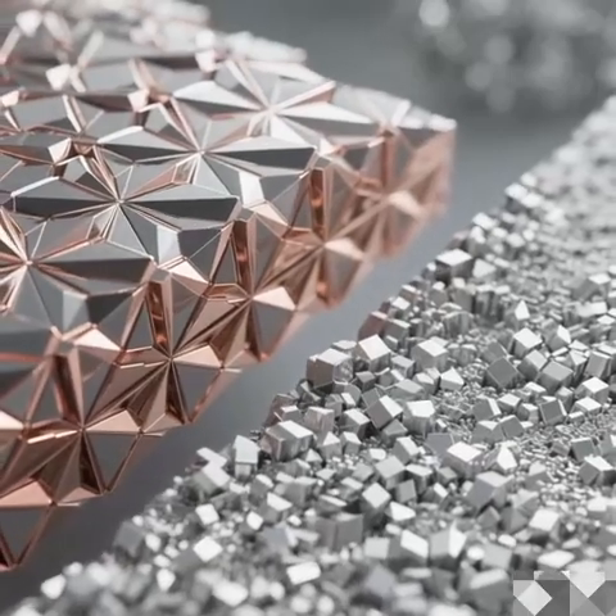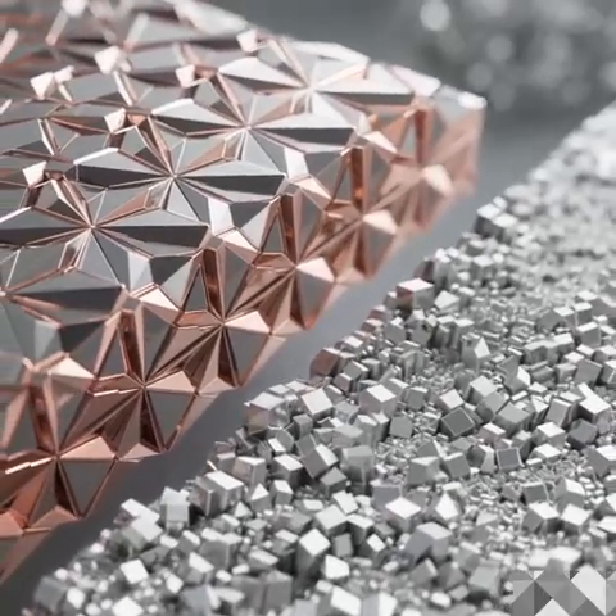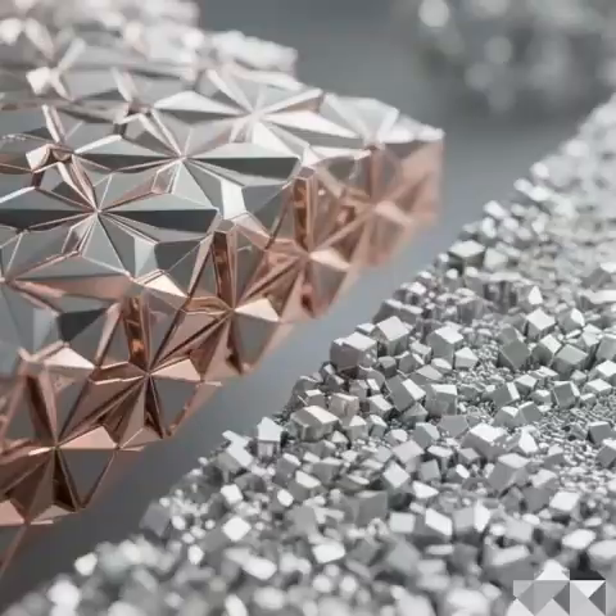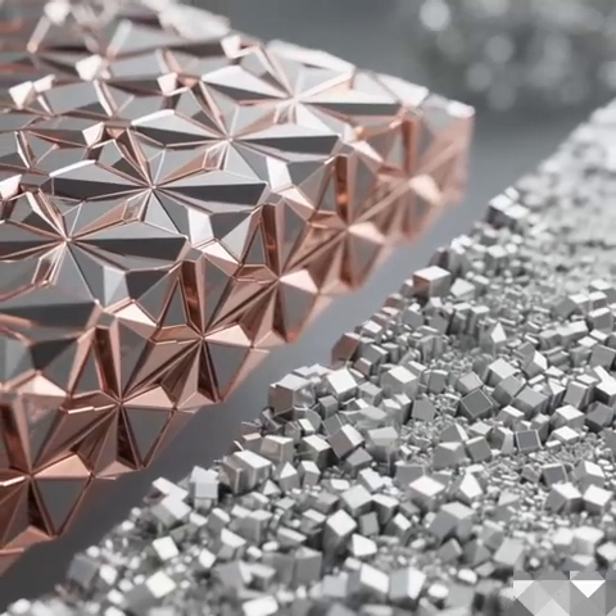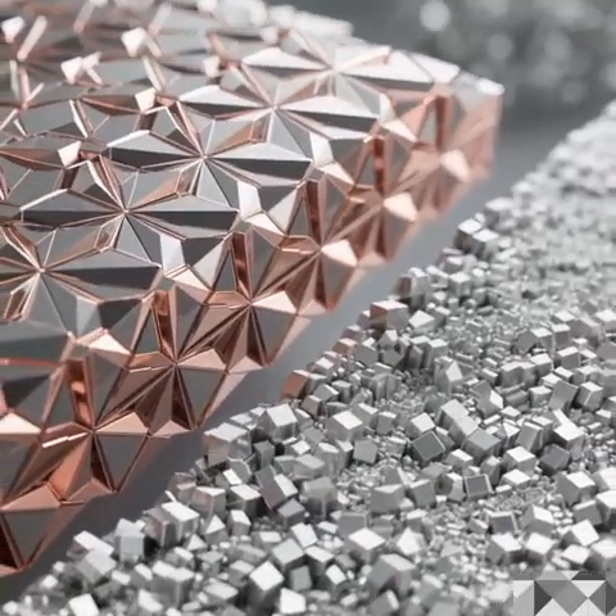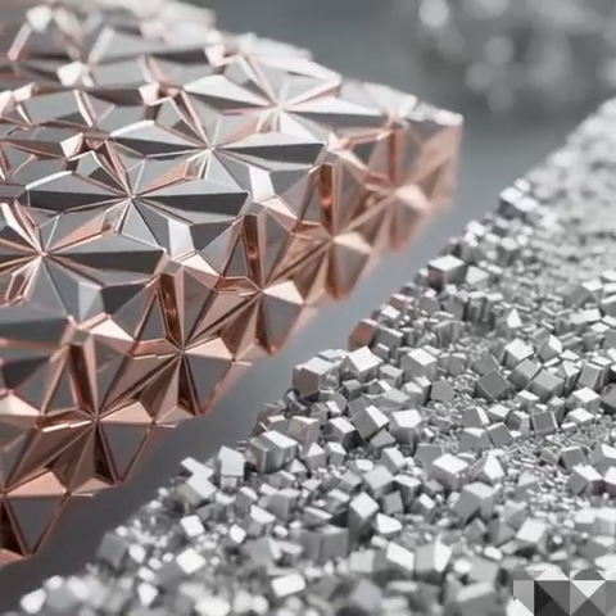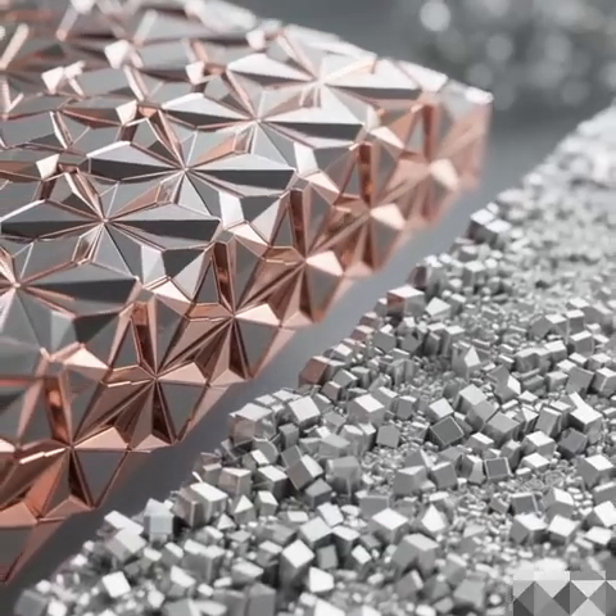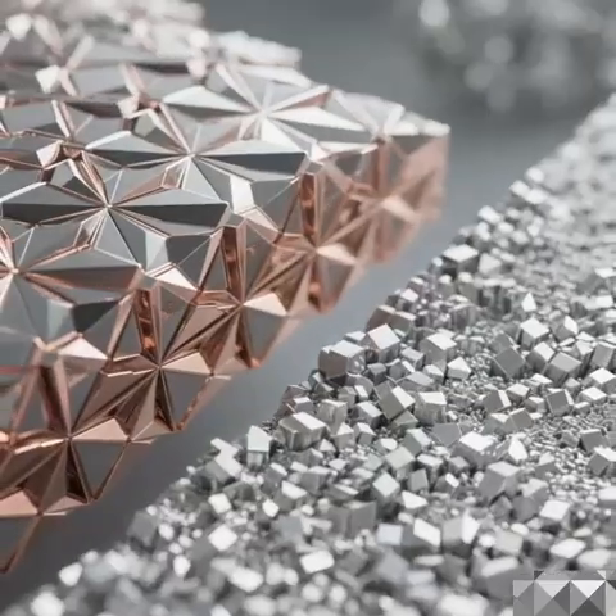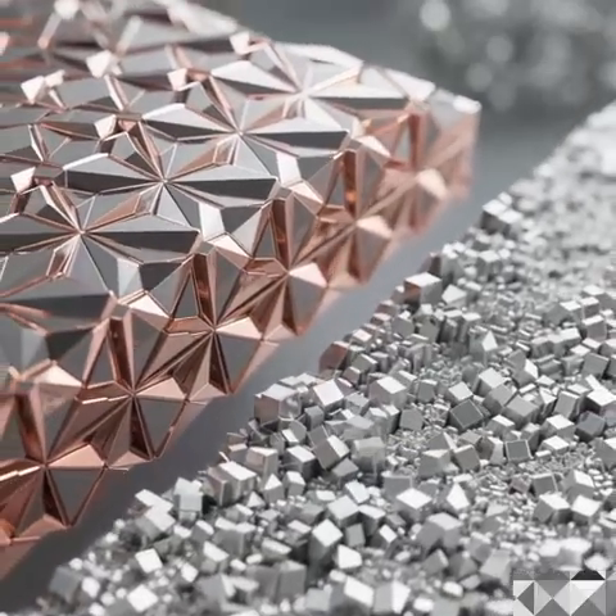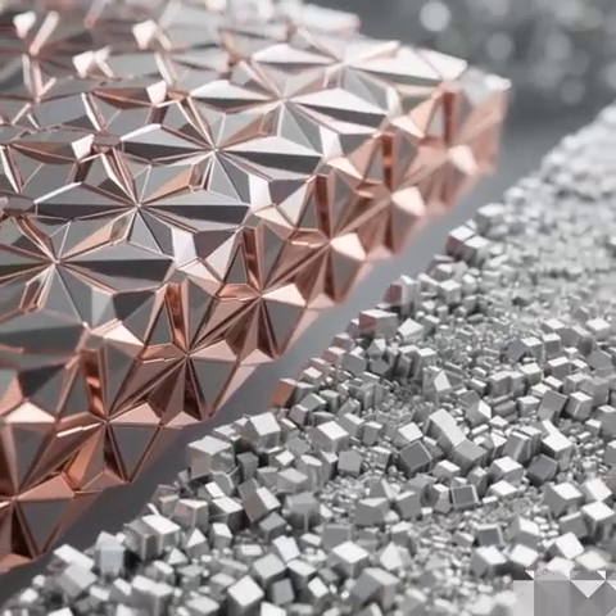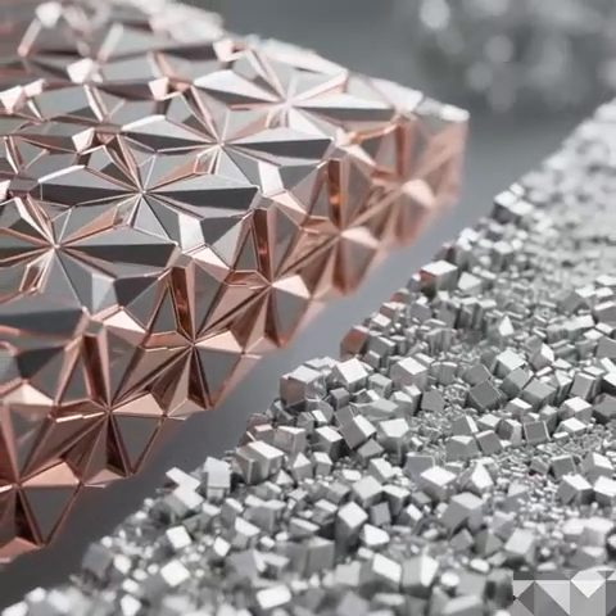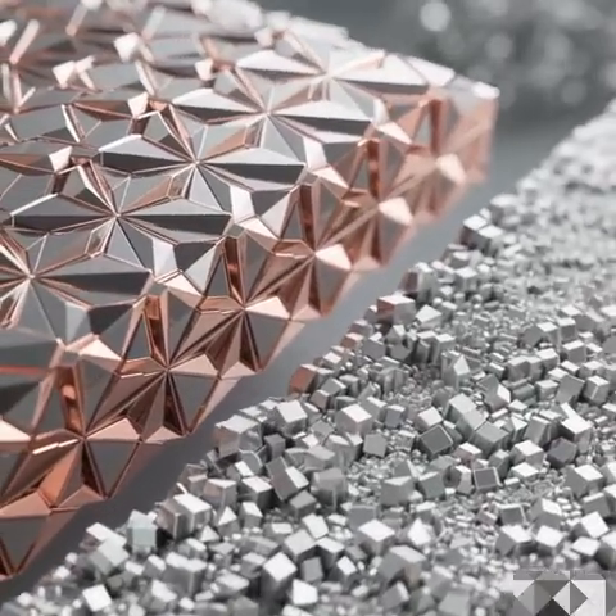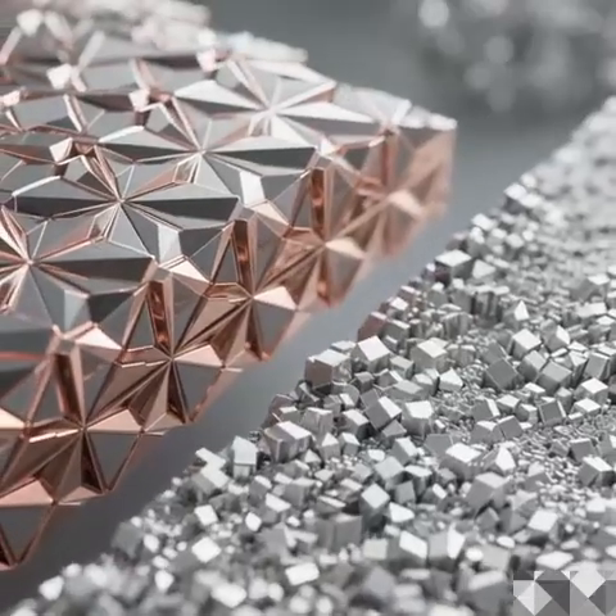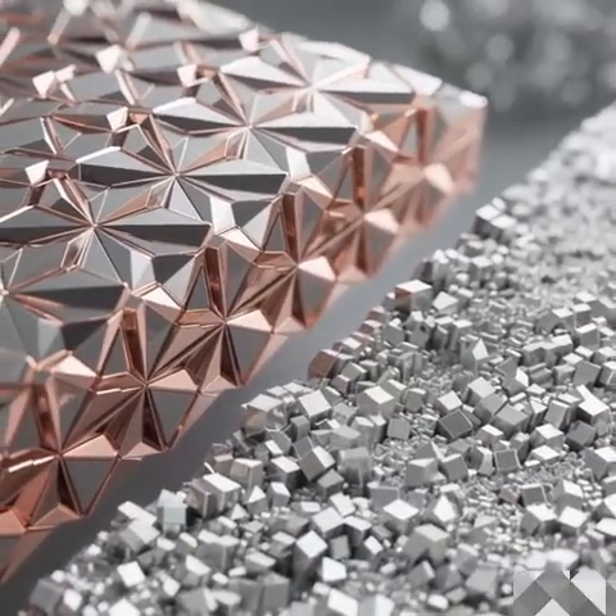That's incredible. And for the real-world impact, this is where it gets really interesting, right? Absolutely. You can imagine stacking chips, like tiny electronic skyscrapers, without cooking the layers underneath. Precisely. That low-temperature, high-quality bond is perfect for things like 3D integrated circuits or bonding a chip directly to a wafer. Especially when you have a very strict thermal budget, you can't afford to heat things up too much. Exactly. You can build complex structures layer by layer without damage.